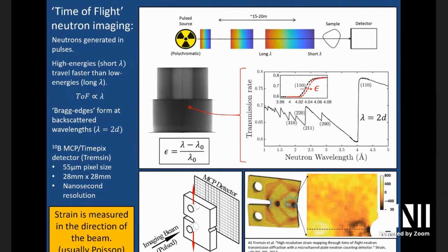And so if you know what that orientation distribution is and you can build it into the model that you're using to fit the edge, then things get easier, right? And also, especially when it comes to scale approximation, right? Because on the one hand, you've got detector pixels of a certain size, so you can't resolve further than that. But within that, which is small, you want to have crystals in lots of different orientations, so they're measuring the strain in every direction there.